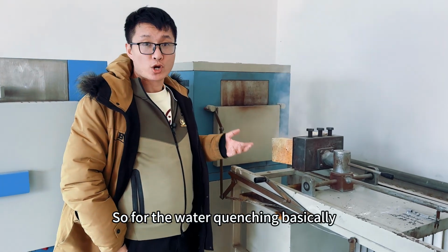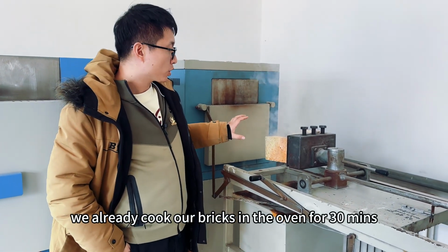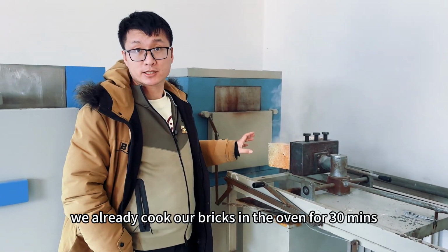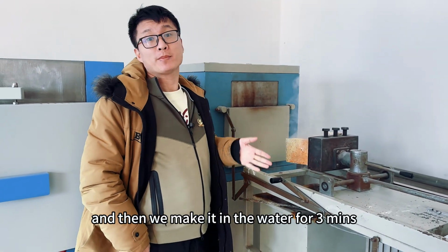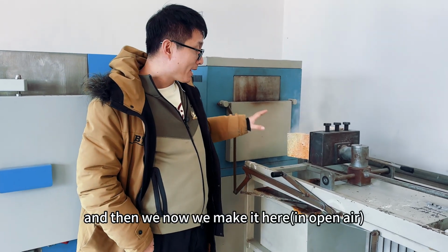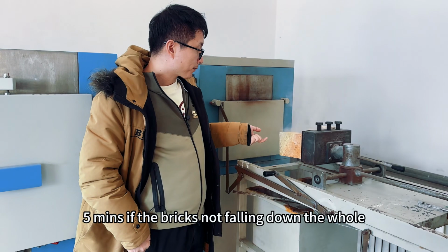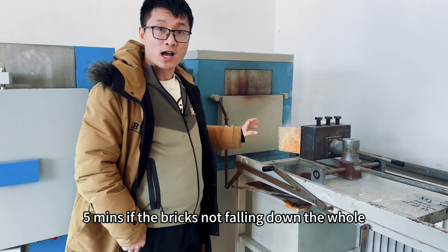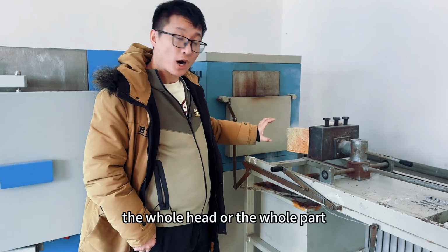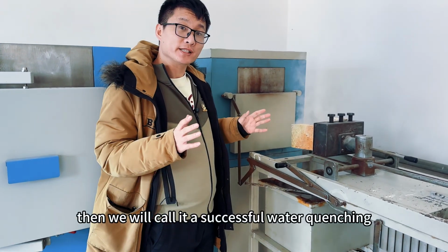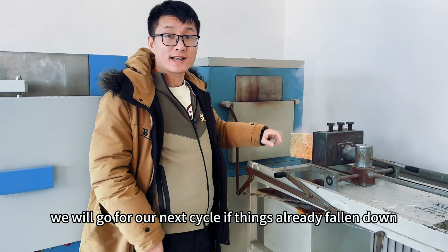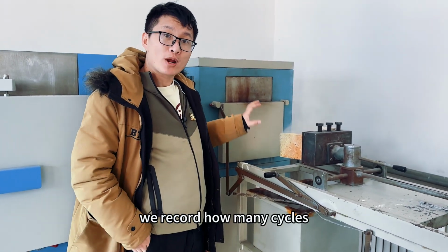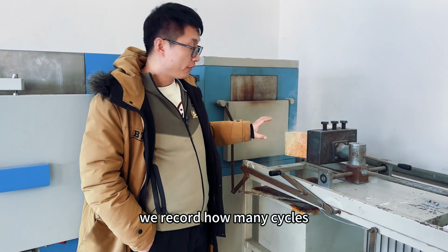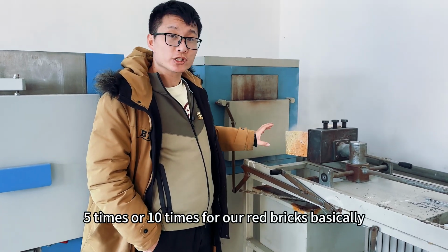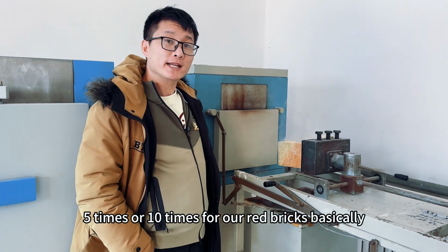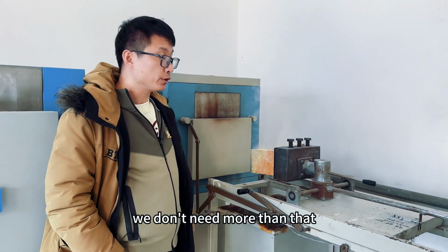For the water quenching, basically we cook our bricks in the oven for 30 minutes, then we put them in the water for 3 minutes, and then we leave them here for 5 minutes. If the bricks don't fall down, neither the whole head nor any part, then we call this a successful water quenching, and we go on to the next cycle. If it falls down, we record how many cycles it has been through, for example 5 times or 10 times. For our red bricks, basically 5 times is our maximum requirement. We don't need more than that.